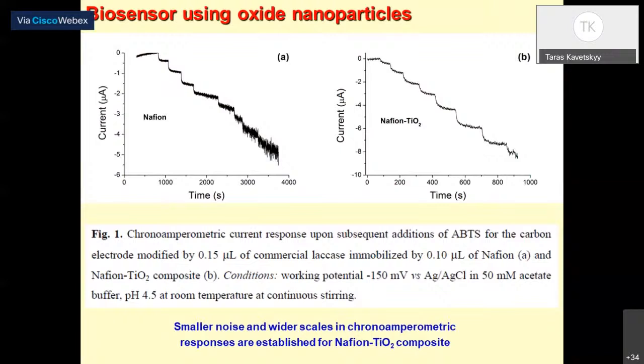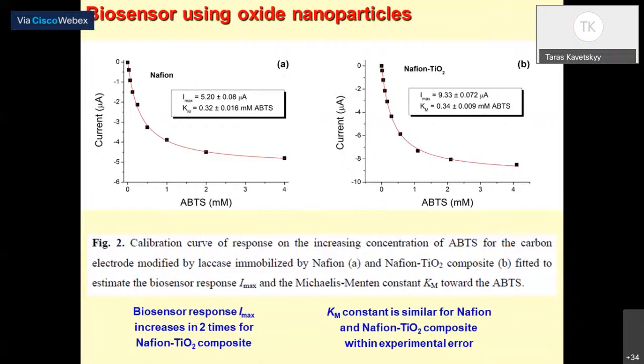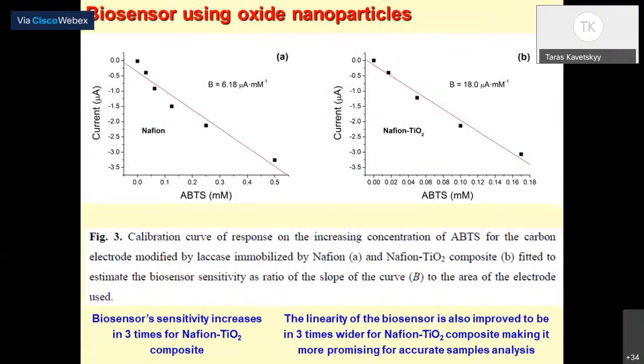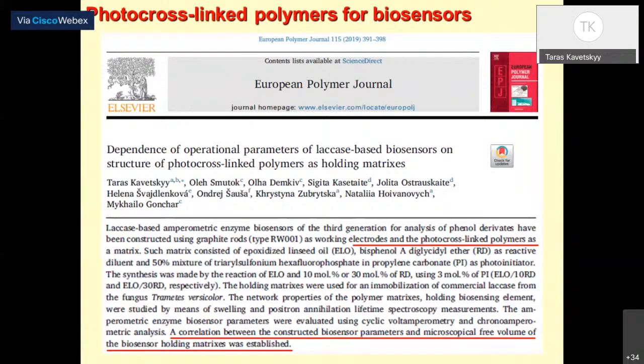The same situation we found using titanium dioxide nanoparticles, as we use a Nafion membrane. We don't see a big difference between values of Km, 0.32 and 0.34. But when we compare biosensor sensitivity, we found that with adding titanium dioxide nanoparticles, biosensor sensitivity increased several times. So after this correlation, we decided to study photocuring polymers, another type of polymers, and we focus on the epoxidized linseed oil polymer with bisphenol A diglycidyl ether as reactive diluent and photoinitiator.